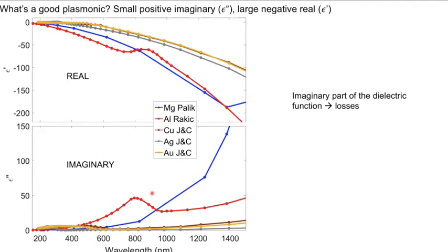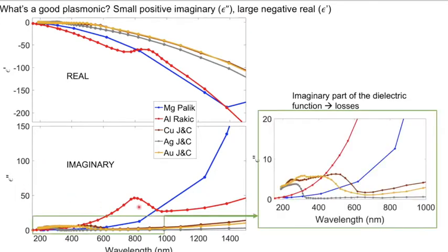Okay, so when you ask yourself what's plasmonic, what you're asking is, well, can you have this resonance, and can this resonance go on without too many losses? And what you want for that is basically a small positive imaginary part of the dielectric function and a large negative real part. The imaginary part is really your losses. Okay. And you can see here that I have the imaginary part, and I'm going to zoom in on this region. That's basically the UV, visible and sort of near IR.